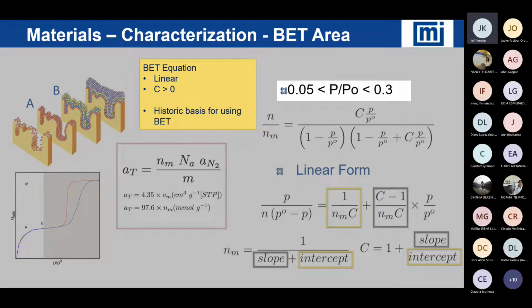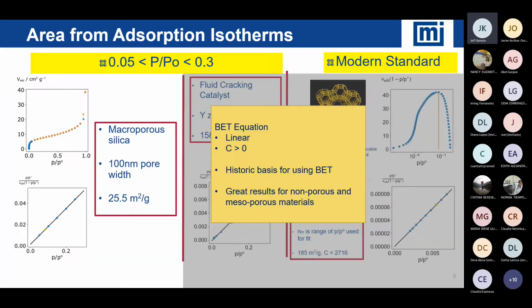So, in absolute pressure terms, we're looking at the adsorption of nitrogen on the surface from about 35 torr up to about 240 torr of absolute pressure. And this worked quite well for reporting surface area of materials.